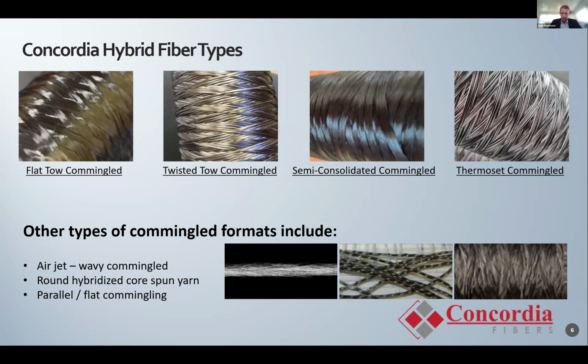The picture in the bottom middle is showing a core spun thermoplastic prepreg tow. So it's very round, it's very tall, and the resin has to flow one tow diameter into the middle to fully wet it out. But it's very consistent. And then lastly, the image on the bottom right shows some other commingled fibers in the industry that are much wavier and less well blended.